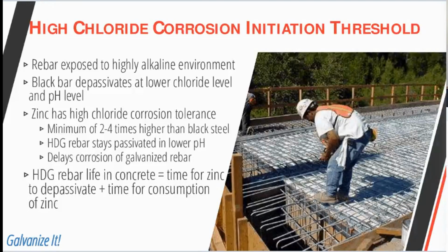For example, black steel is passive in an alkaline concrete until the chloride concentration level exceeds a certain threshold, about 1 pound per cubic yard. Then we know that the black rebar starts to corrode. Meanwhile, zinc can withstand a chloride concentration in concrete, which is 2 to 4 times higher than black steel. So this actually delays when the coating will start to corrode by several decades.